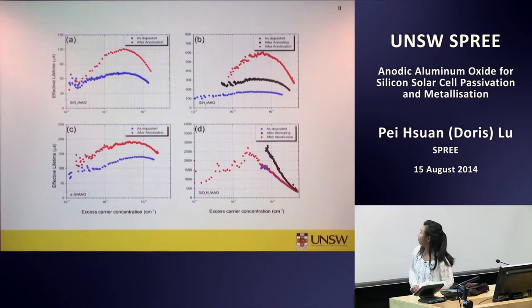Those are the effective lifetime as a function of excess carrier concentration. After anodization at the high injection level, the lifetime is nearly identical to the as-deposited one.